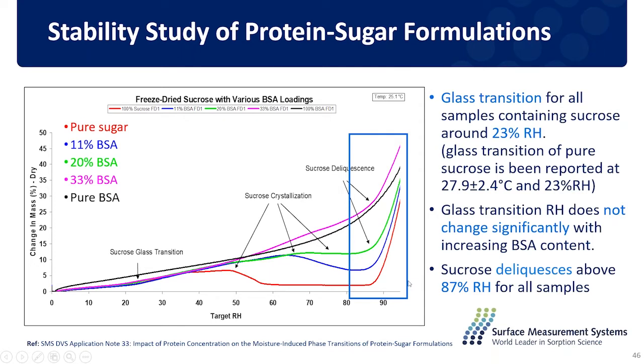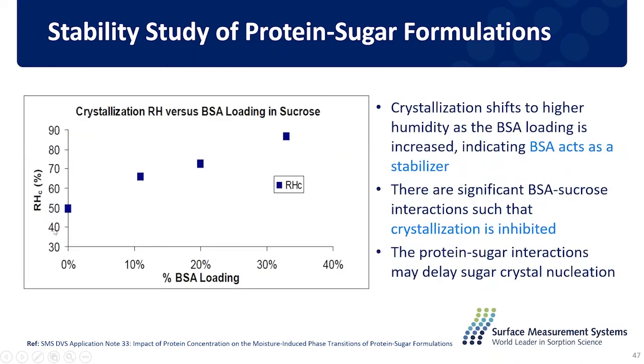So we did the same experiment at 25 degrees for the mixture samples as well, to study how the protein concentration will affect these three different points. What we notice here is that the glass transition is just overlapping, which means protein has very little impact on the glass transition of the sucrose. But for the crystallization point, with the increasing of the protein concentration, the crystallization point is shifting to a higher level. So basically, with more protein in the mixture, the sample is more stable at higher relative humidity against crystallization.